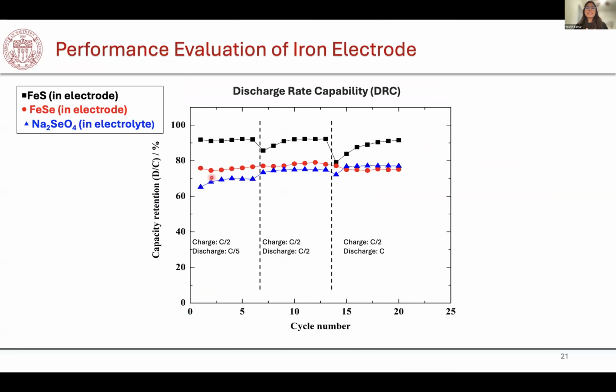And as you can see, the capacity retention for iron sulfide is slightly higher compared to selenium-based additives. But what I want you to take away from this slide is that for selenium-based additives, whether present in the electrode or in the electrolyte, the capacity retention is well maintained, going from very low rates of C/5 discharge to very high rates of 1C, which tells that this additive can serve as a good depassivating agent and was able to attain good discharge capacities at various discharge rates.